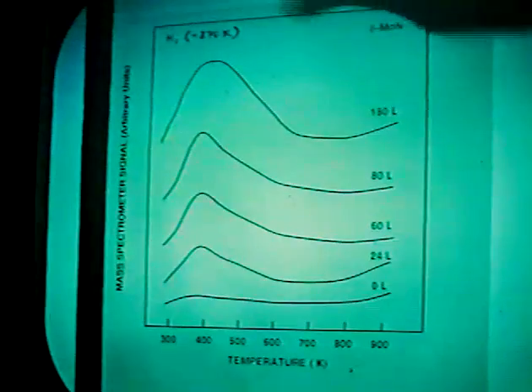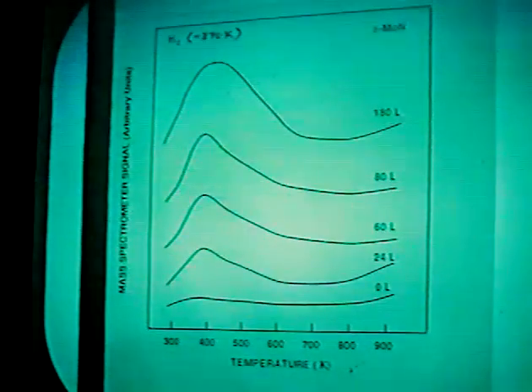When we now take a look at some of these phase pure thin films, and this is just an example, the beta film, if we do hydrogen TPD, and this is all in a UHV system, you notice that there are 2 peaks. As we increase the dose, the centroid of this peak here does not change. That's characteristic of a first order desorption process. The gamma film, very similar characteristics. We have 2 peaks, a low temperature and a high temperature peak. Again, as we increase the dose, the centroids of the peaks do not change significantly.